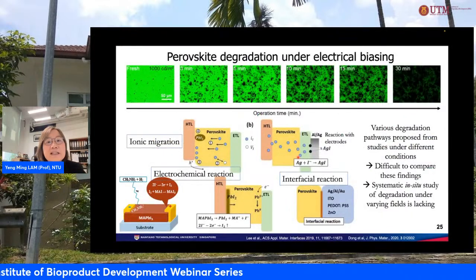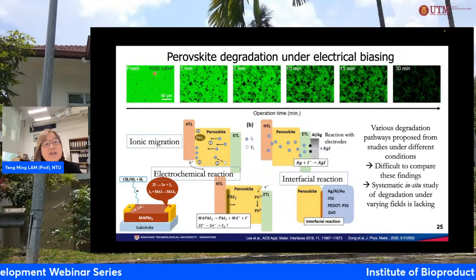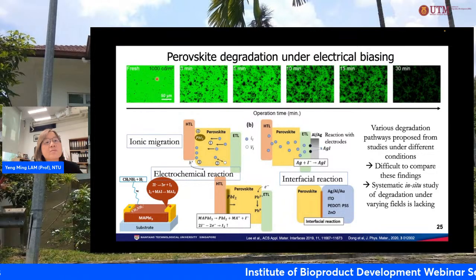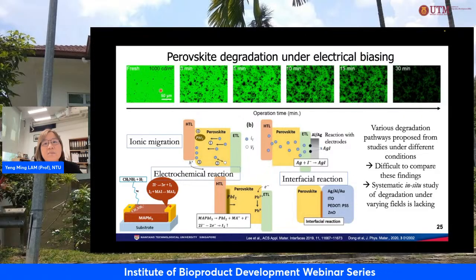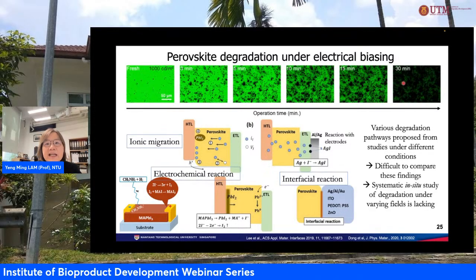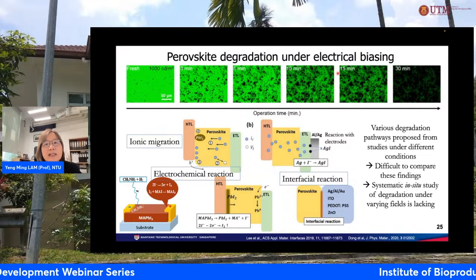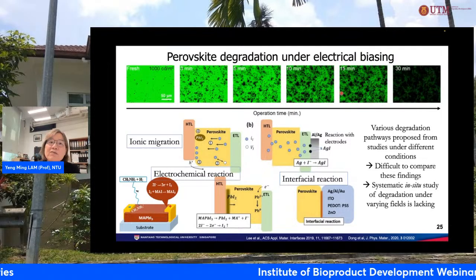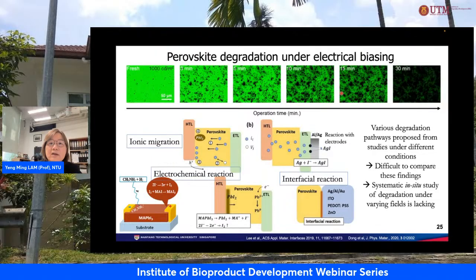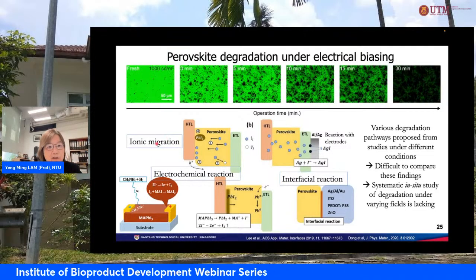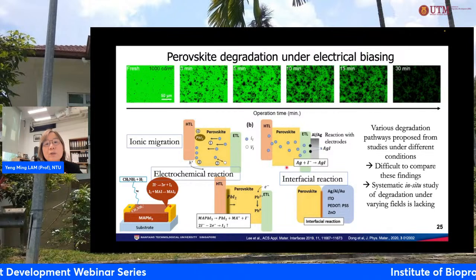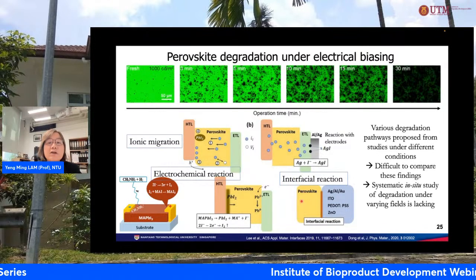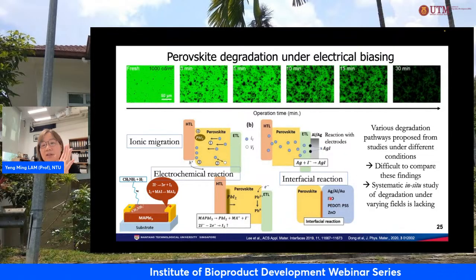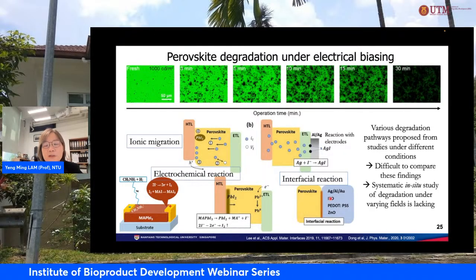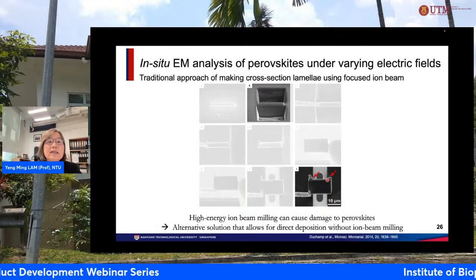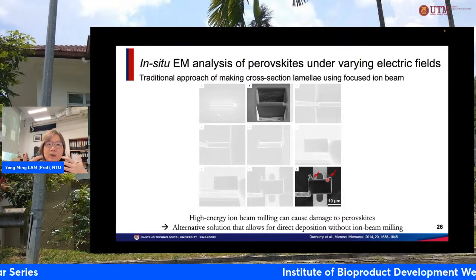So if you look at perovskite degradation under electric bias, this is a luminescent material. A fresh material will look very luminescent, bright green. But over time, you will see that it loses its luminescence. In fact, it loses 90% of its luminescence by 13 minutes. So this is very fast degradation. It's not very useful as a material. The reason for this degradation is ionic migration, electrochemical reaction, and also interfacial reaction. So this perovskite material is very reactive to any of this electrode material that comes into contact with it. So very fast degradation.